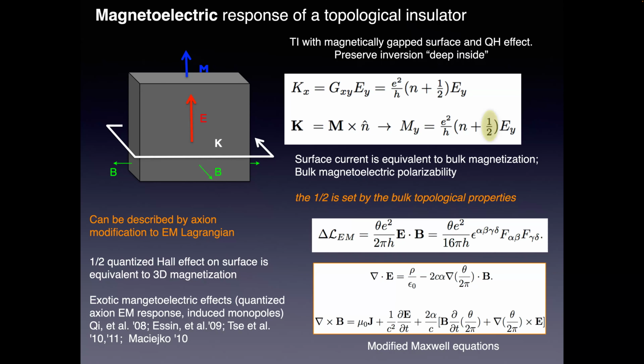Whereas in chromium sesquioxide, this magnetoelectric coefficient, the proportionality between, let's say, electric field and magnetization, is just some number, like the conductivity of copper. It's a number that we might be able to measure, or predict if we had a good enough theory, which we never do. In the context of topological insulators, that proportionality is e squared over h times 1/2.